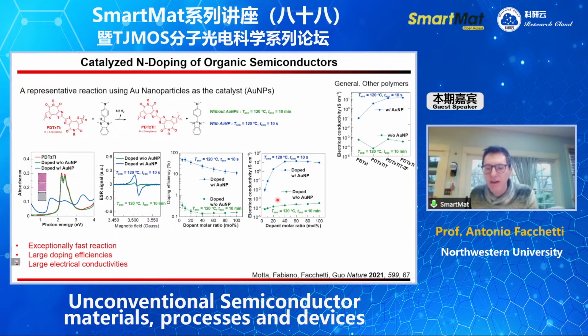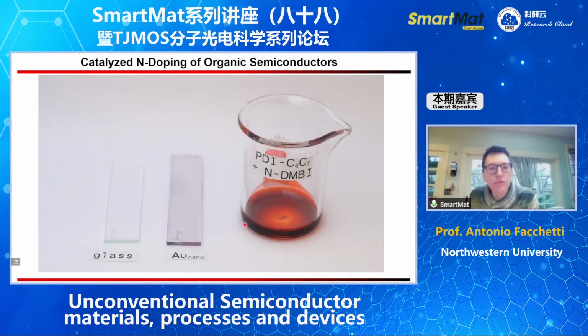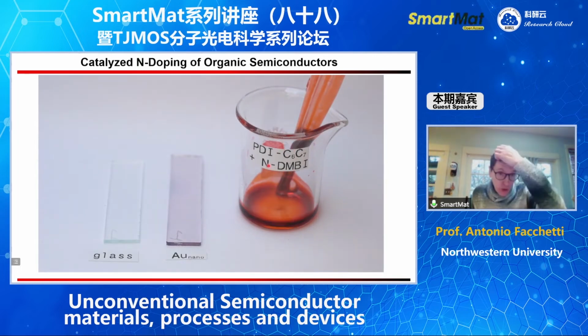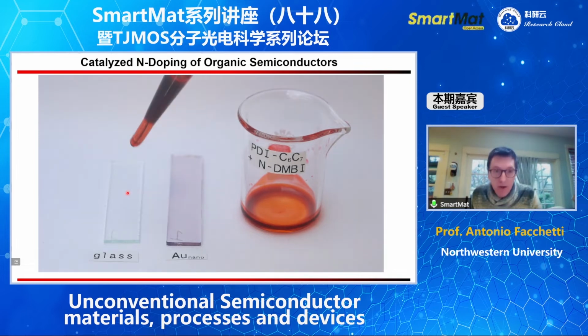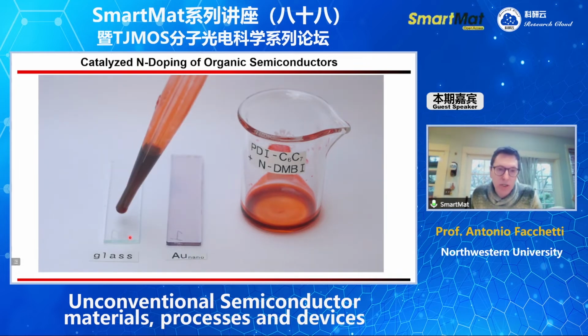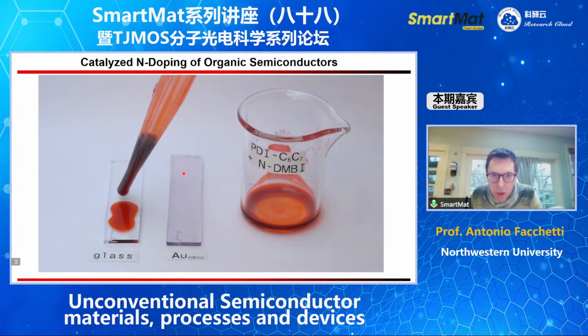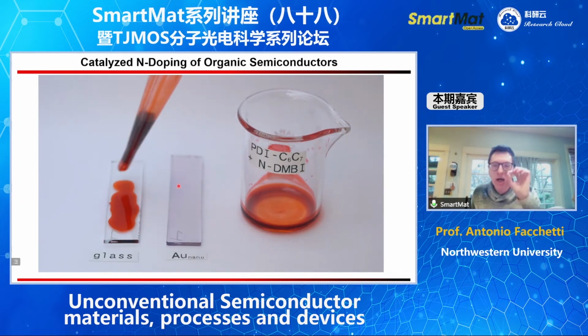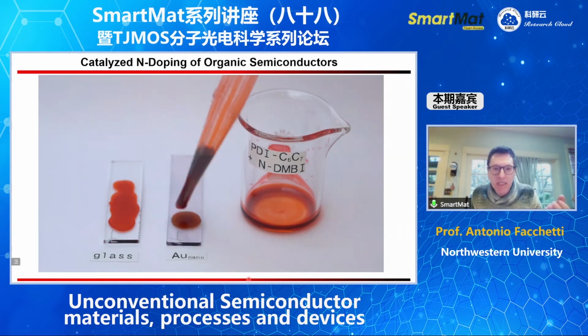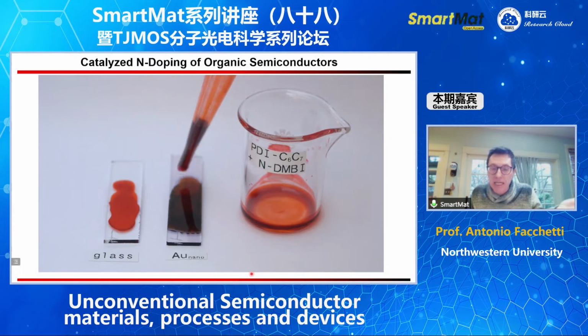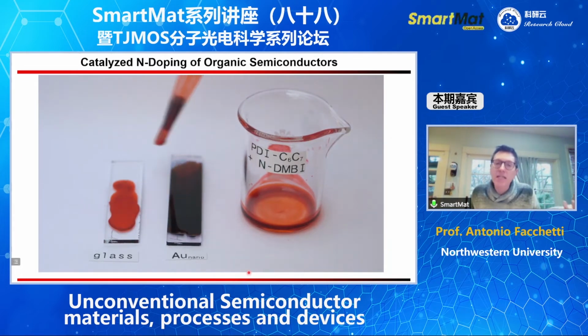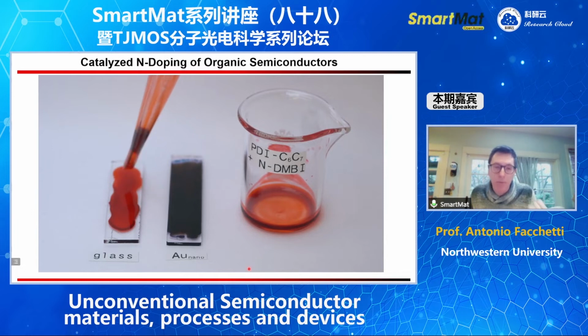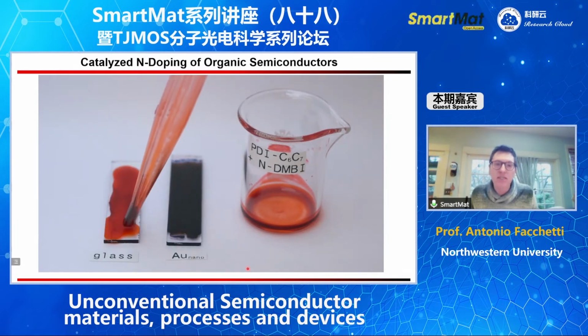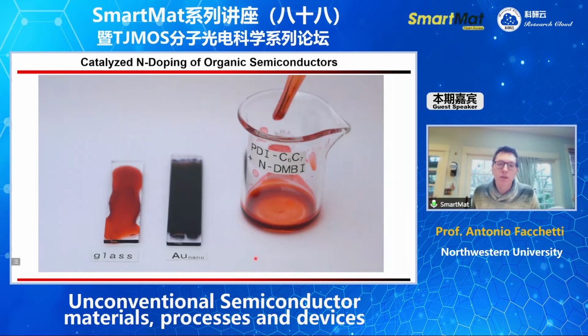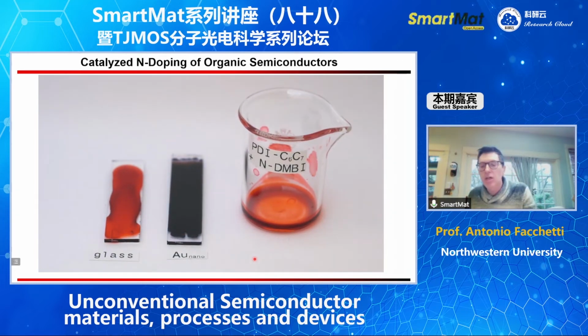And the reaction is extremely fast. I don't know if this video is going to start, but let's see if it does. So this is an example of the blend solution. And here we put the solution in air on a glass slide, where here there is no catalyst. The catalyst is deposited, and you see the slight variation in color, which are the nanoparticles. And here there are the nanoparticles, and you see the reaction occurs basically immediately at room temperature. So nominally, the reaction occurs at 120 degrees, but in practice, the reaction is extremely fast, very, very efficient, and it results in very large conductivities.